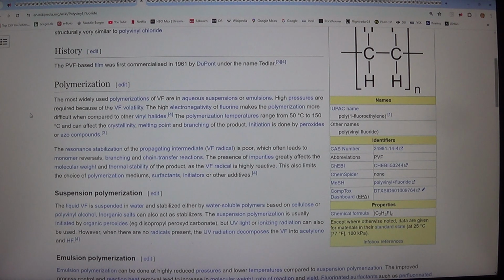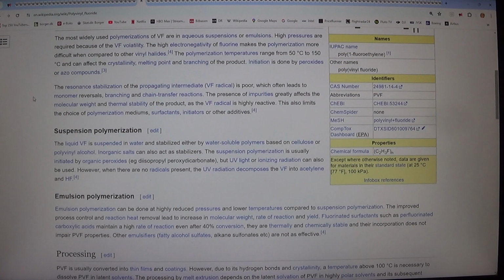The resonance stabilization of the propagating intermediate, the VF radical, is poor, which often leads to monomer reversals, branching and chain transfer reactions. The presence of impurities greatly affects the molecular weight and thermal stability of the product, as the VF radical is highly reactive. This also limits the choice of polymerization mediums, surfactants, initiators or other additives.